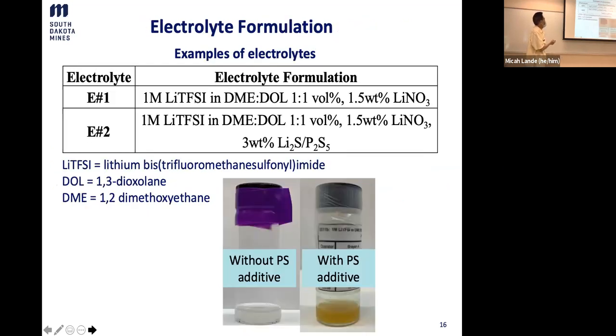And then another approach: I want to give some example of the electrolyte formulation work. Here I just chose two examples, E1 and E2. You can see that for lithium, the electrolyte has lithium salt, LiTFSI, in the formulations here, dissolved in the DME and the DOL here, and then we add a little bit of the additive lithium nitrate, and this is E1. For E2 we add a little bit more polysulfide. Once you do that, the electrolyte turns a little bit brownish, and that's still usable. Sometimes when it turns brown, you say, well, it's bad. But this is actually a normal electrolyte in this case.